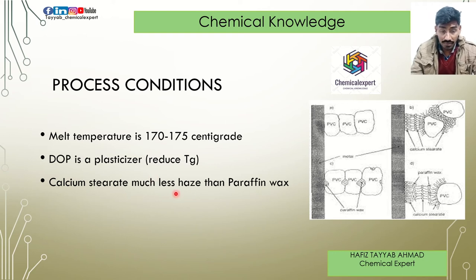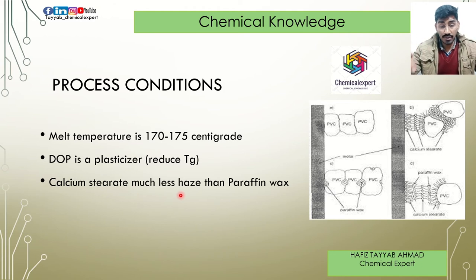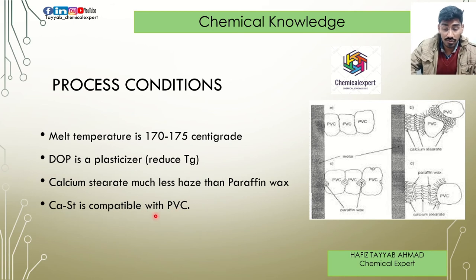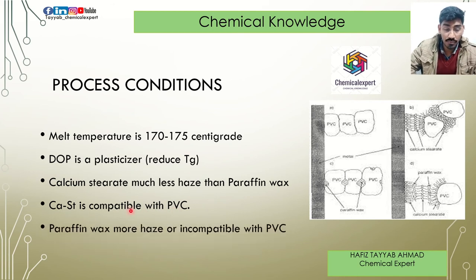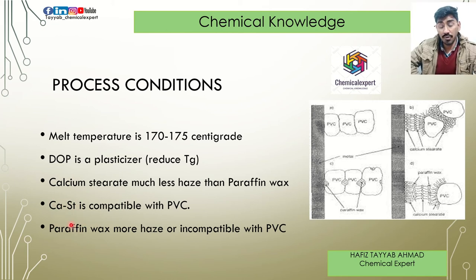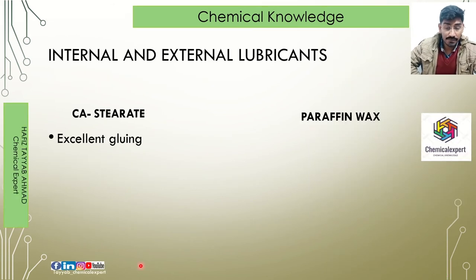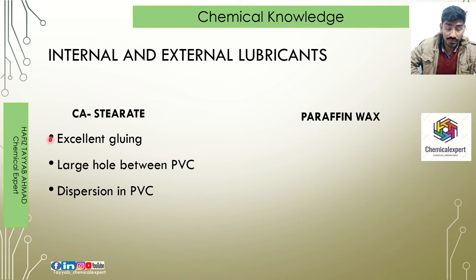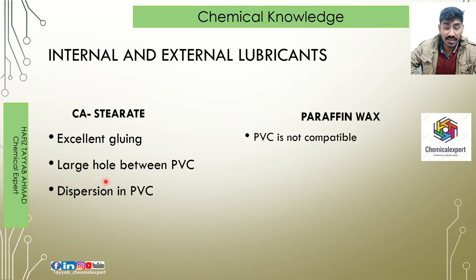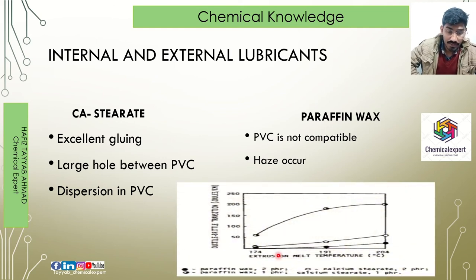Calcium stearate produces much less haze than paraffin wax. Haze refers to fusion agglomeration or a mist-like occurrence. Calcium stearate is compatible with PVC and is very helpful. Paraffin wax, on the other hand, is more incompatible with PVC and causes more haze. We should use both together — paraffin wax as external lubricant and calcium stearate as internal lubricant. Calcium stearate also gives excellent dispersing ability, helping pigments and other additives disperse easily.